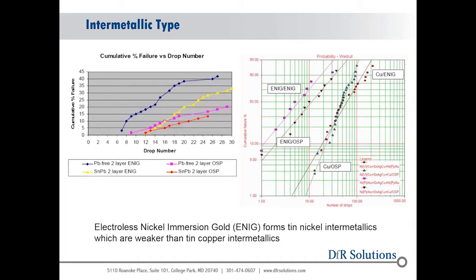And as we can see on this chart here on the right, the number of drops to failure for the copper tin intermetallics is quite significantly higher. So, if you're going into a high shock level environment, you may be better off going with the OSP or HASL type of finish because you're getting a stronger intermetallic. The other thing, though, is ENIG is really good for elevated temperature applications because at higher temperatures, the tin nickel intermetallic grows quite a bit slower than the tin copper intermetallic, so it's usually better for high temperature applications. So there's things you have to consider about all the different board finishes and how they impact the shock robustness of the product.